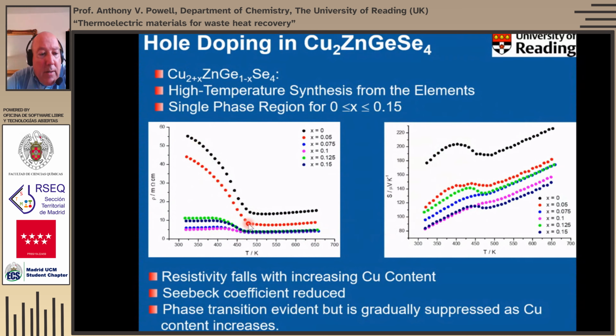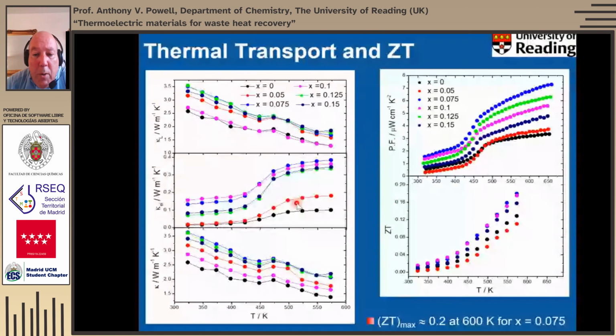And we think that that's because there have been some calculations that suggest that the copper defect formation energy is increased as we make copper-rich phases. So it becomes more difficult for those copper ions to delocalize and for that copper sublattice to melt partially. So we get thermoelectric properties. I won't go through these in detail, but again, the power factors are increased as a result of those changes in the transport properties.